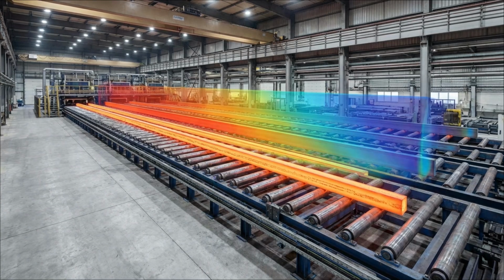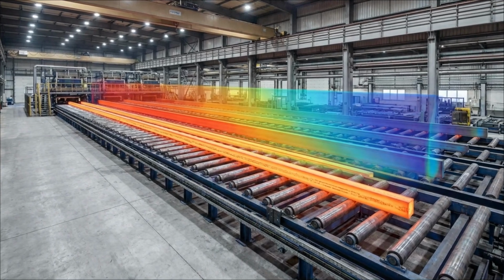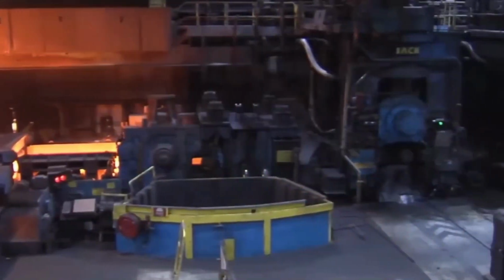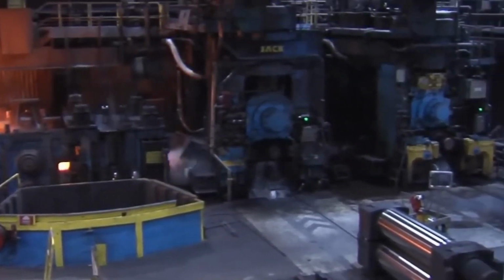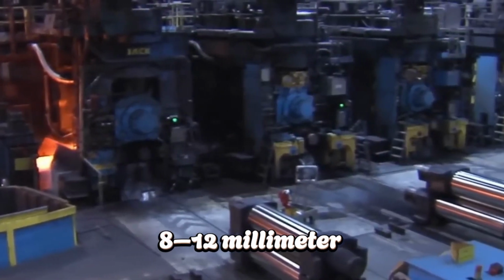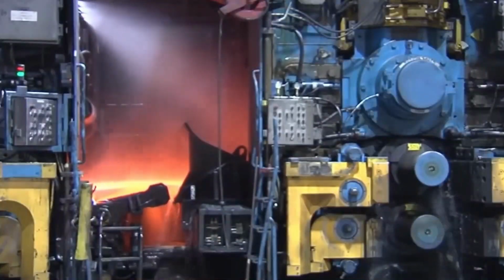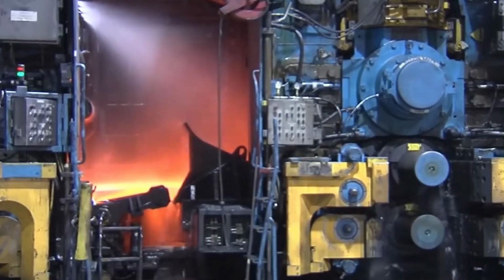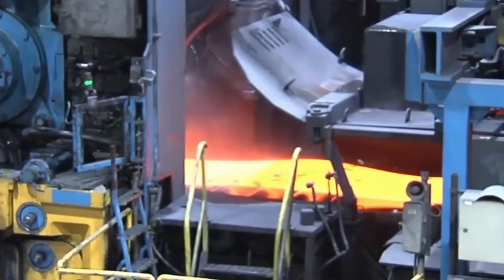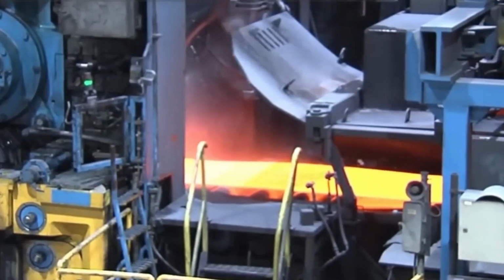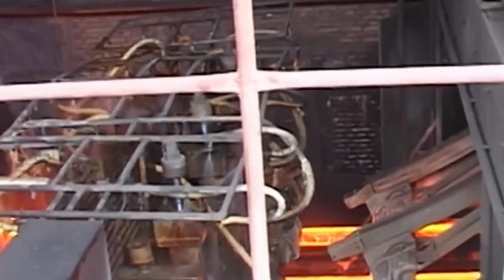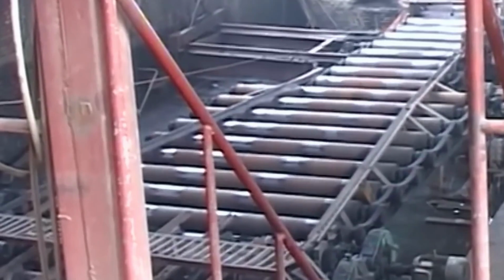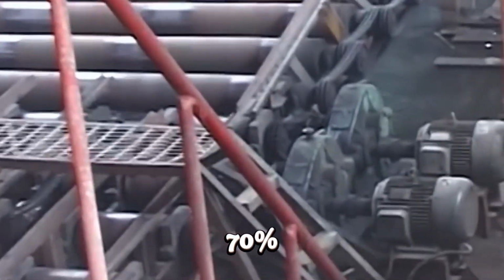The mold must cool and move at the same time, or the steel freezes in place. The copper mold cools the outer layer instantly, forming an 8 to 12 millimeter shell. It oscillates 20 to 40 cycles per minute to prevent sticking. Lubrication powder melts on contact, forming a glassy film that keeps steel from welding to the walls. Since the 1950s, curved casters replaced ingot molds, cutting defects by over 70% and enabling continuous withdrawal control.